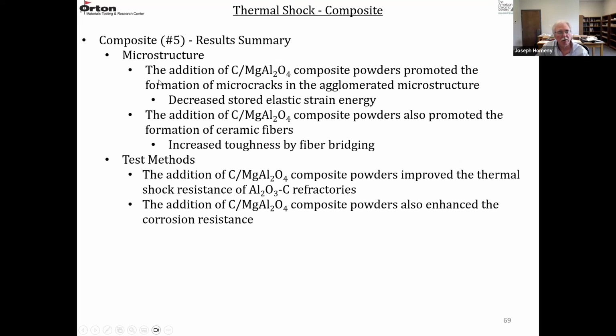So in this experiment, the addition of these graphene, carbon, spinel composite powders promoted the formation of microcracks. And this is an agglomerated type microstructure that decreased the stored elastic strain energy. The addition of these composite powders also promoted this rod-like ceramic fiber formation, and they attributed the increase in thermal shock resistance to fiber bridging. In terms of the test methods, the composite powders improve the thermal shock resistance, and the composite powders also enhance the corrosion resistance.